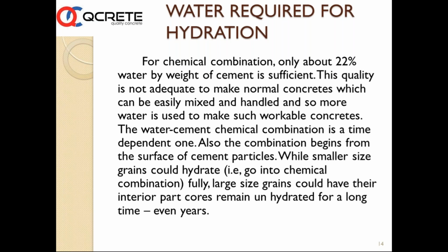The 2.5 micron particle hydrates very fast, while the 25 micron one keeps on hydrating. So sometimes at 28 days, what is available as cement still has an unhydrated core, whereas the shell has already started hydrating and giving strength. So this goes on even beyond 28 days.